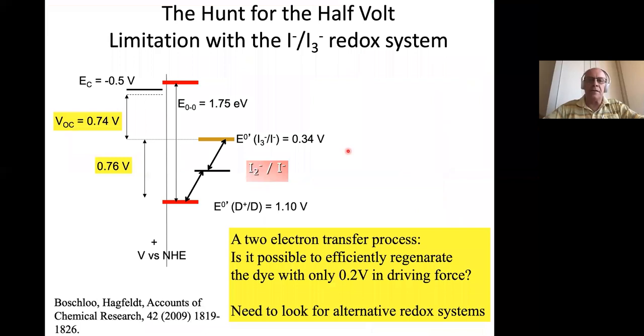And the starting point for our research back in Uppsala, with Gerrit Boschloo, we started to look into how to improve this. Iodide typically at best gives 10% efficiency. And we started to think how to move it up to maybe 15%. And the question was, where are the main losses? And it's no secret, and we knew it from the very beginning almost, that the big drop in potential we lose internally in the system is between the redox potential of iodide and the potential of the oxidized dye. Here we typically have a gap of 0.7, 0.6 volt. And that is something we lose internally in our system.